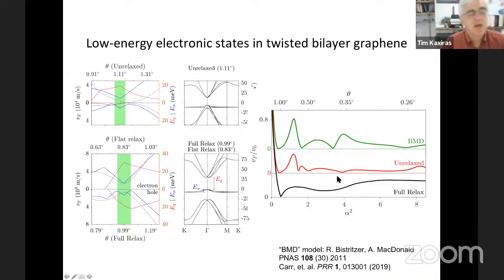Okay, so here's also a comparison with the Bistritzer and MacDonald model. This is the green line. This is a quantity called alpha square, which is basically proportional to 1 over the twist angle. So as alpha becomes larger, the twist angle becomes smaller. And this is the region around 1 degree. The Bistritzer-MacDonald model predicted a 0 value for this quantity, which is the magic angle at this point, and it also predicted other 0 values. So there was the suggestion that there may be several magic angles. If you have a model without relaxation, these minima are roughly at the same places.